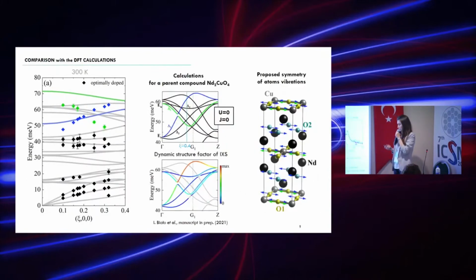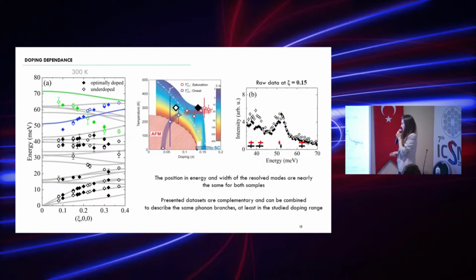Now I'm adding to the previous picture points for the underdoped sample. And as you can see, they are at pretty similar places. So these two data sets are very similar within experimental error, so they can be named complementary. So the conclusion is we don't see any doping dependence. And at the beginning I said that the charge density wave order phenomenon is really doping dependent. So what I'm saying is that there is no influence of charge density wave order on the dispersion of phonon modes along copper-oxygen planes. And that's kind of important.